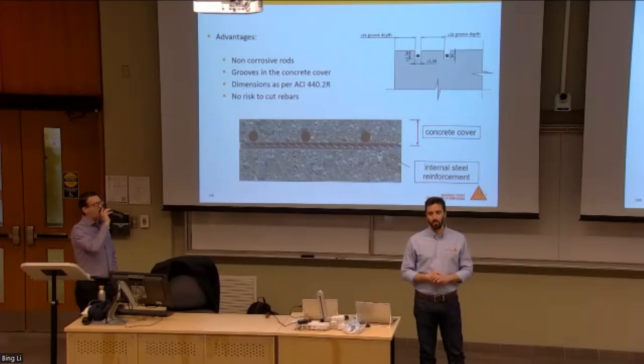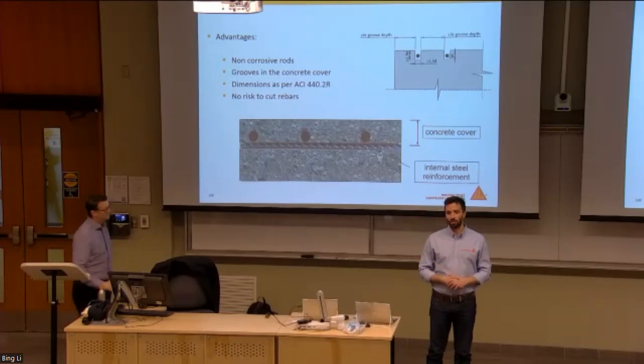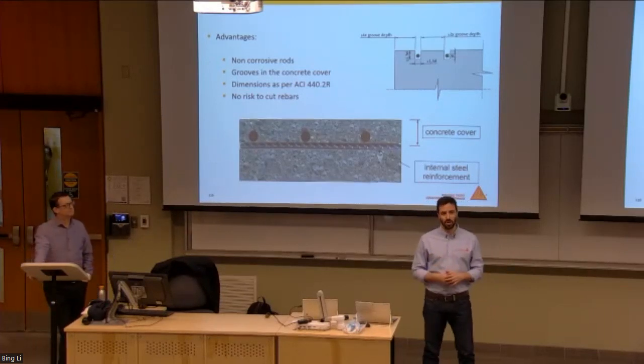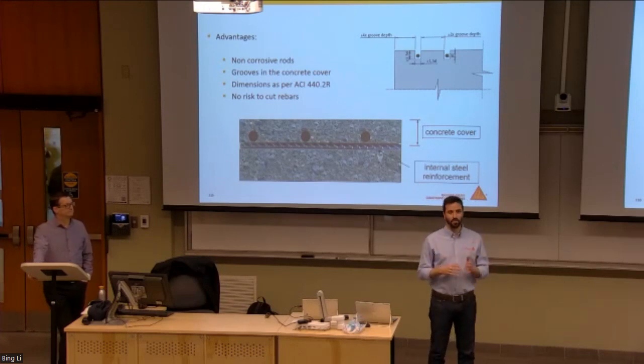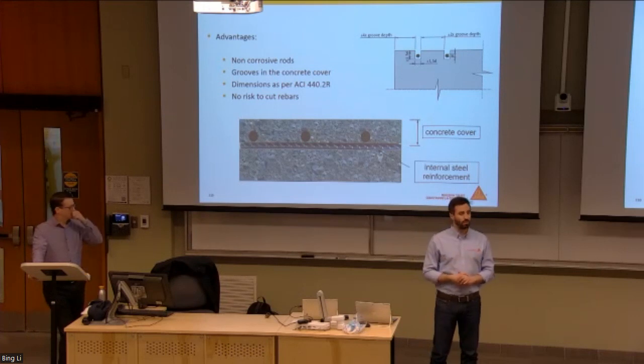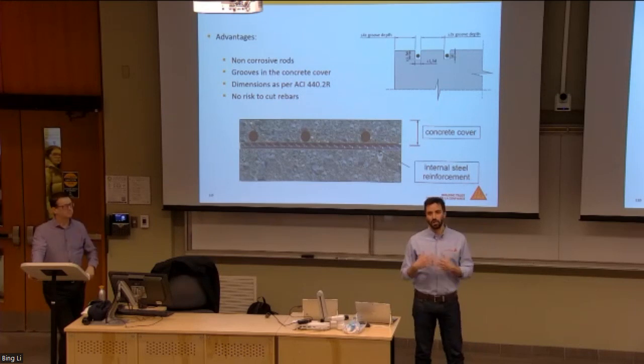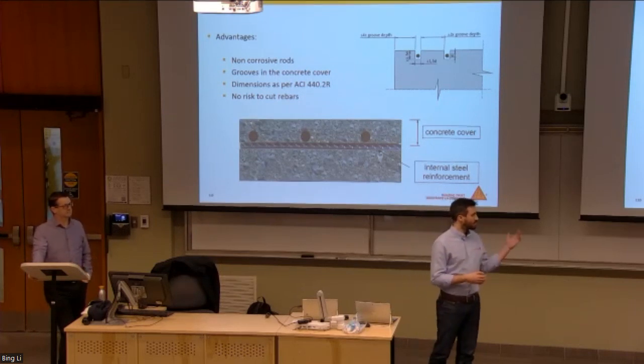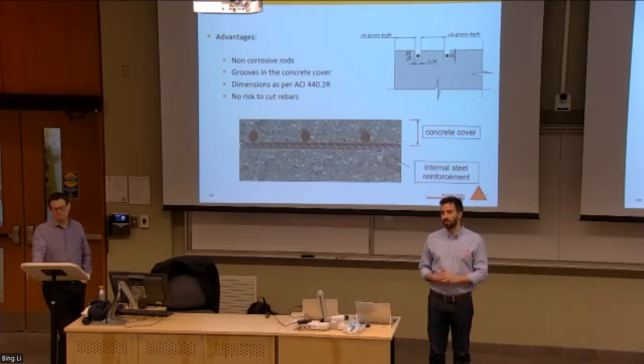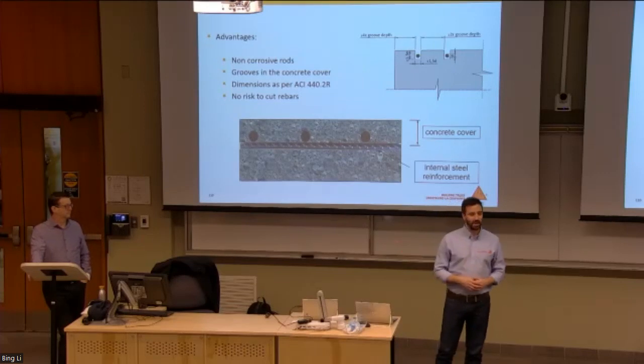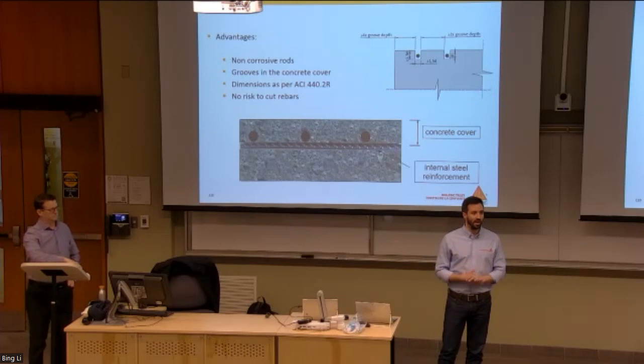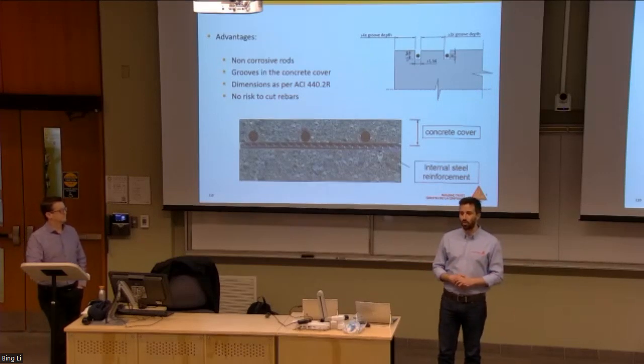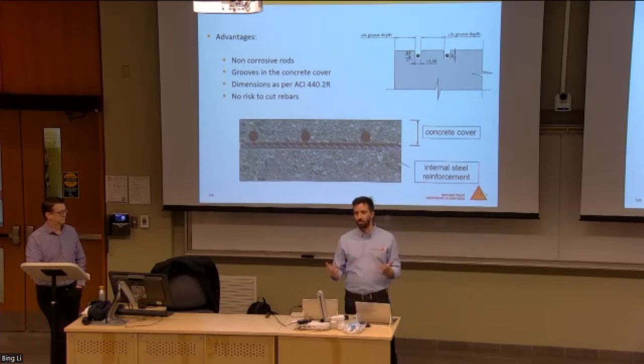At Sika, we always recommend following the national or international design code. So the ACI 440, Bruce mentioned this code earlier. It gives all the dimensions of the groove based on the diameter of the rod. Everything is explained in the code, and Sika follows the code for the design and the application. Normally there is no risk of cutting rebars in the concrete, but as Bruce was saying, the engineers have to check first that you are not too close to the rebar, just in case, because we don't want to damage the concrete structure before reinforcing it. So that's really the idea: put the resin into the groove and then install the CarboDur rods in the groove.